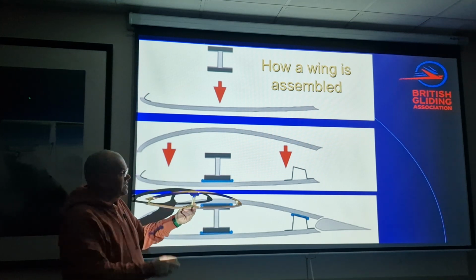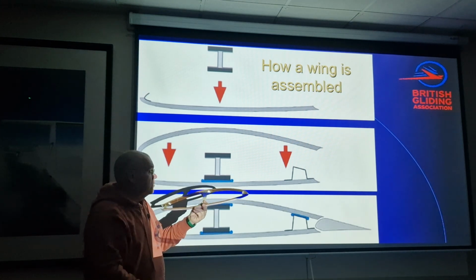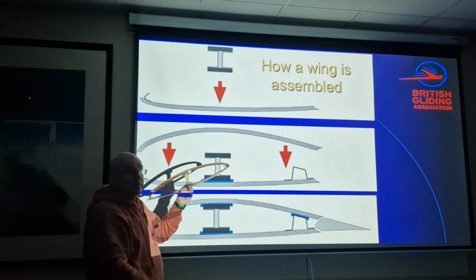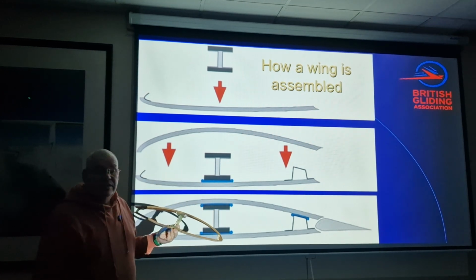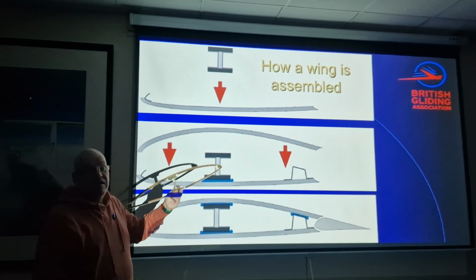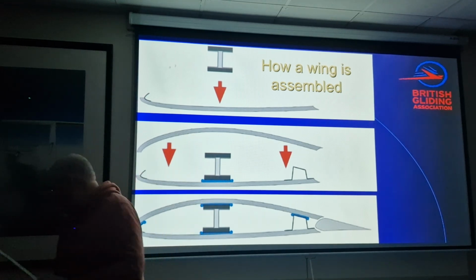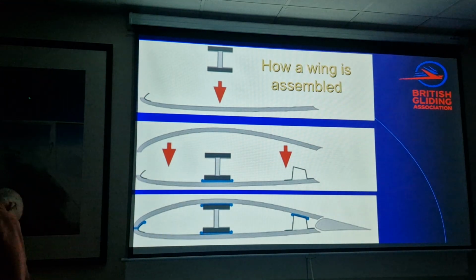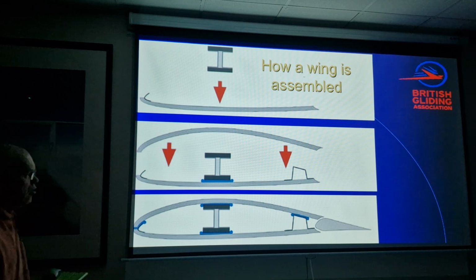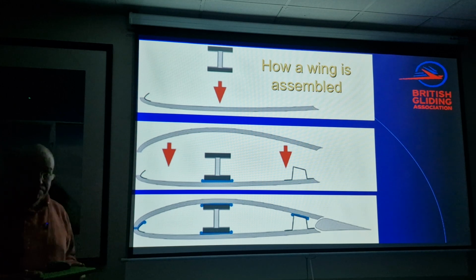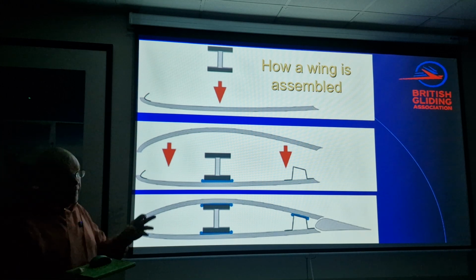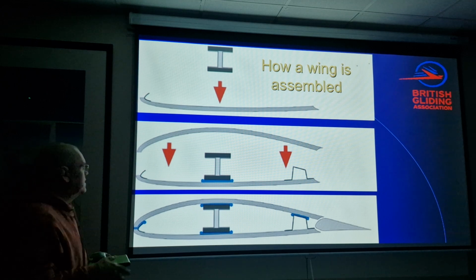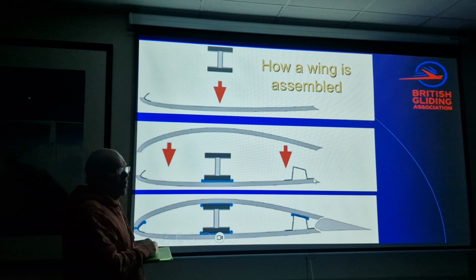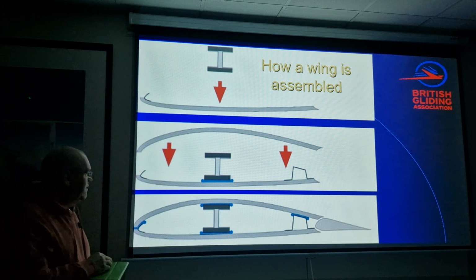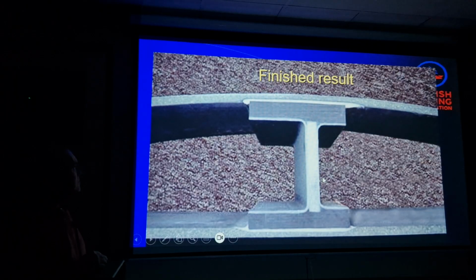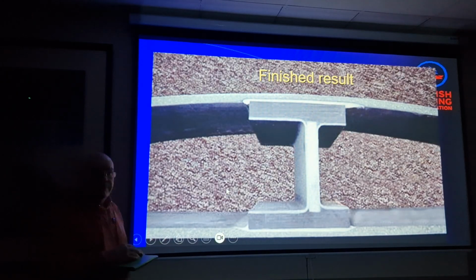So, but the foam, once it's built, is just dead. And it's literally just polystyrene foam. Would you believe the back ends of Nimbus 2s and Astirs are made of polystyrene foam? Absolutely true. And if you cook that to 80 degrees, it melts. So when you're post-curing it, you really go to 54 degrees and no more. It has different properties. It's not called polystyrene, but it is identical to polystyrene. And that is an ASG29 wing.